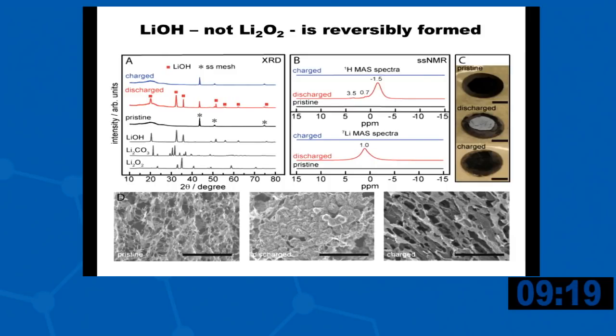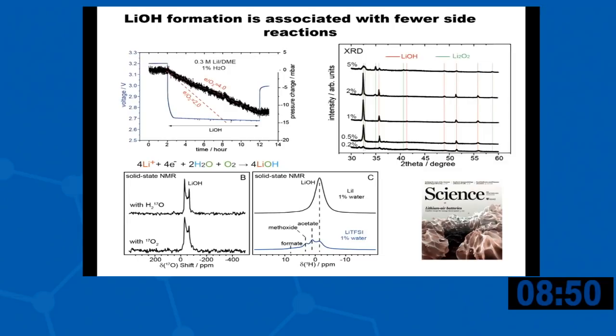And so the only thing I wanted to point out in this system, that instead of forming lithium peroxide, we actually change the chemistry and we form lithium hydroxide. And we form these monstrous, again, particles. We can actually do this reversibly. And what's interesting is because we form a hydroxide, not a peroxide, we get dramatically reduced amounts of degradation products. And we can see the degradation products in the proton NMR confirming this.